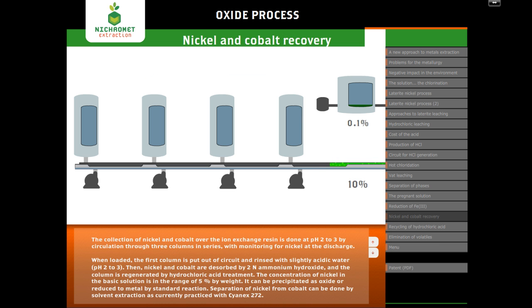The collection of nickel and cobalt over the ion exchange resin is done at pH 2 to 3 by circulation through 3 columns in series, with monitoring for nickel at the discharge. When loaded, the first column is put out of circuit and rinsed with slightly acidic water. Then, nickel and cobalt are desorbed by 2-N ammonium hydroxide, and the column is regenerated by hydrochloric acid treatment. The concentration of nickel in the basic solution is in the range of 5% by weight. It can be precipitated as oxide or reduced to metal by standard reaction. Separation of nickel from cobalt can be done by solvent extraction as currently practiced with Cyanex 272.